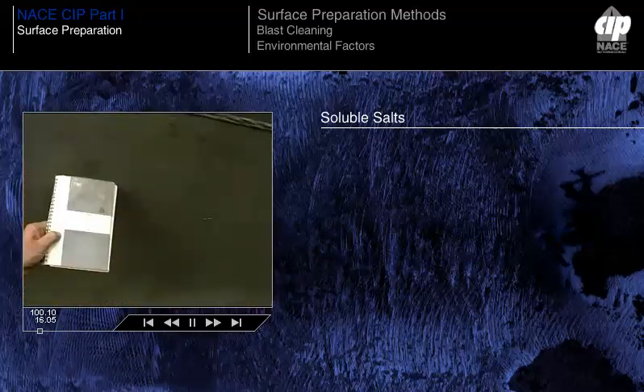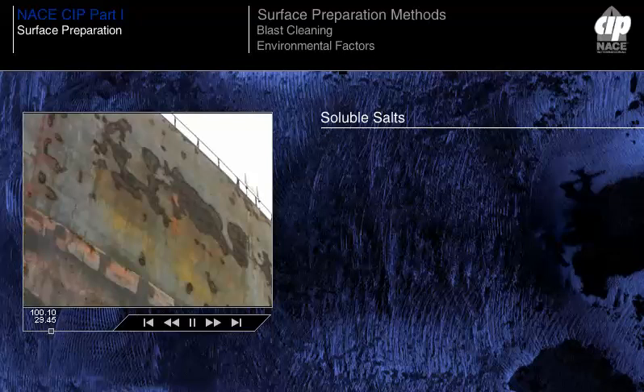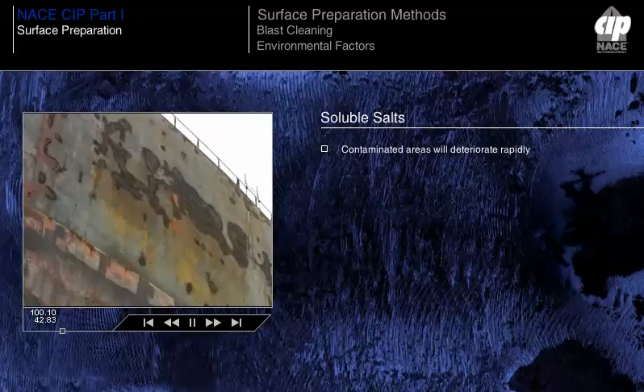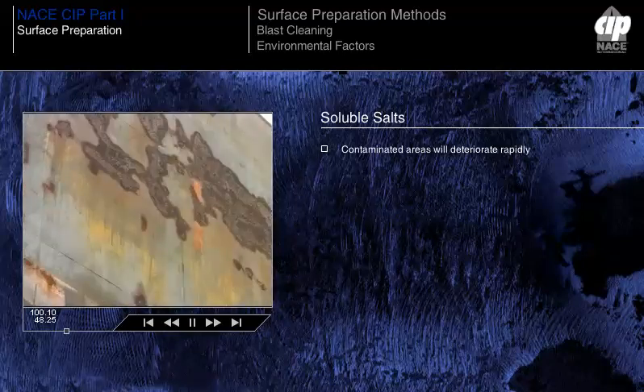Even though the surface may appear to be properly blast cleaned and free of corrosion products, it may contain enough non-visible contamination to create a surface unsuitable for coating. In extreme cases, heavily contaminated areas will, after blasting, absorb moisture from the air, turn dark and rapidly deteriorate. This effect can sometimes be seen within minutes of completion of the blast cleaning process, particularly when humidity is relatively high. It is a clear indication that the surface is still contaminated.